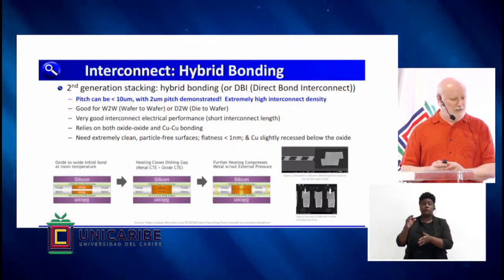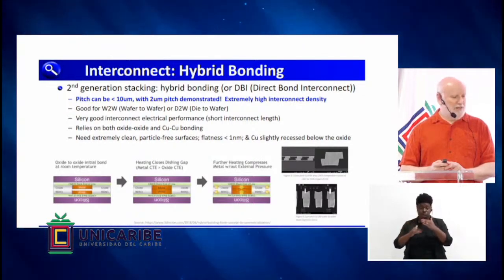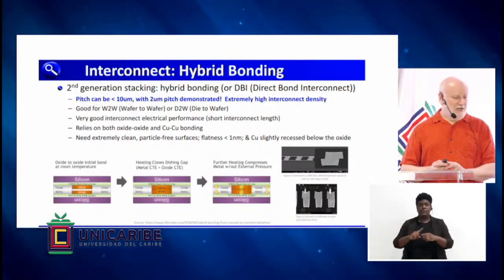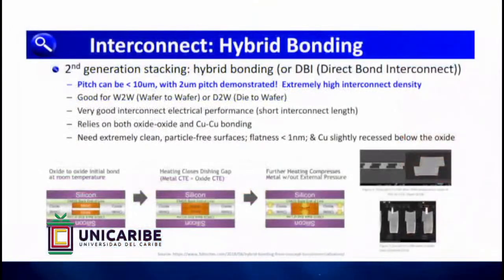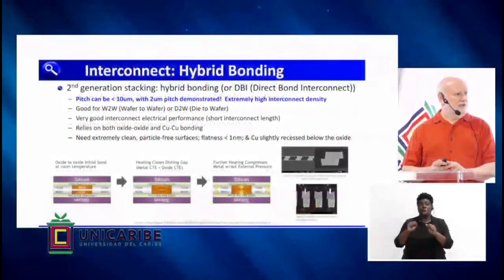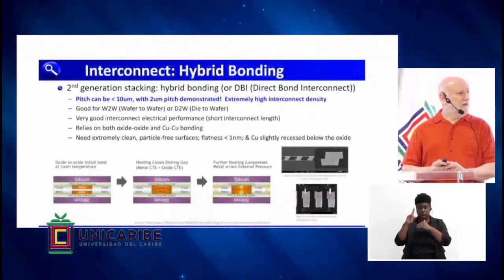And essentially what you're seeing at the bottom are two different wafers. And this works only with copper interconnect processes. So you have to have a copper layer at the outside, and you planarize this copper layer, and you activate it with a plasma, and you bring the two wafers together. And the copper is formed within an oxide, silicon dioxide dielectric layer. And those oxide layers will bond and hold the two wafers together, and then you apply heat, and the heat expands the copper, and when they touch, they start to interdiffuse. So it's a very low temperature process, but the good thing about it is that it essentially can be done at the scale and the density of whatever the interconnect layer is you have on the wafers. So extremely tight pitch.